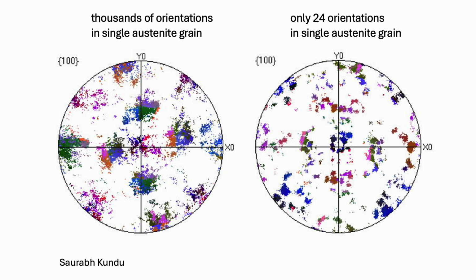And what you see is that we produce many thousands of orientations of martensite plates in a single austenite grain, which all crystallography would tell you that in the undeformed grain you can only get 24 variants. So by producing a huge confusion of orientations of martensite plates, you deflect any cracks that form tortuously through the structure, and therefore the toughness increases dramatically in the untempered condition.